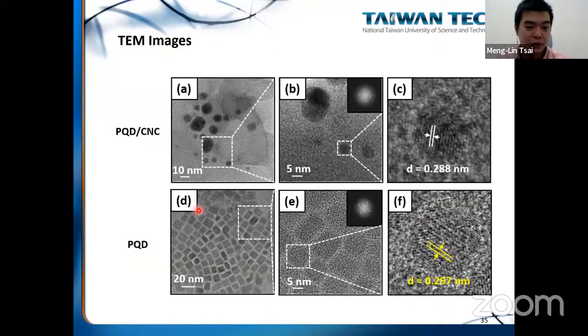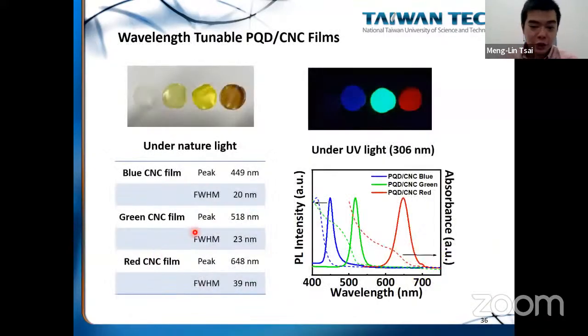Okay, and we also perform the TEM image, okay, to compare that the perovskite quantum dot within the cellulose nanocrystal. And this one is for pure perovskite quantum dot without using the cellulose nanocrystals. Okay, and by tuning the halide element, okay, we can actually control the emission wavelengths of our film, okay, from blue light to red light.